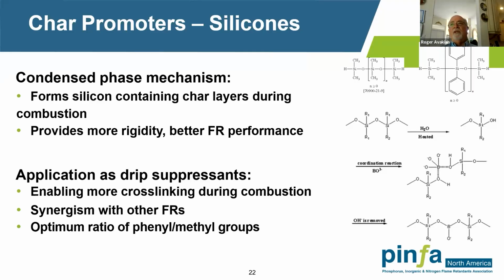Again, it provides more rigidity, so it kind of holds that molten polymer in there, so it does not drip. It forms a pretty nice, basically non-permeable char layer, acting as a barrier to prevent oxygen ingress and prevents decomposition flammable gases from escaping and fueling the flame. Typically, not all silicones work the same way, and there are certain molecular weights and typically a blend of the methyl as well as the phenyl substituted materials that work the best. There's been a lot of work in that area on which materials work best.